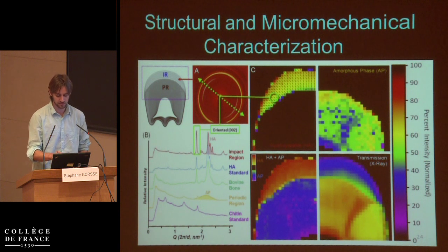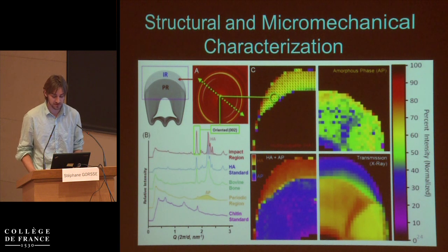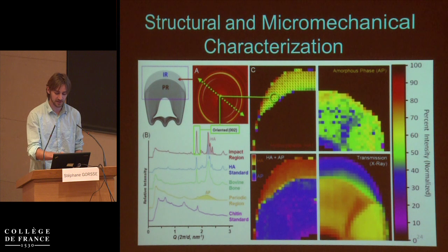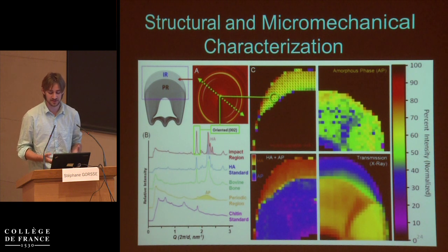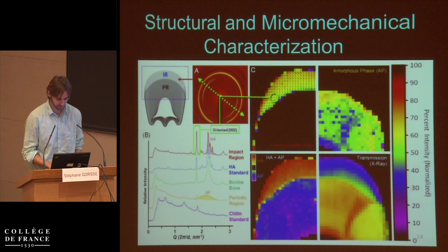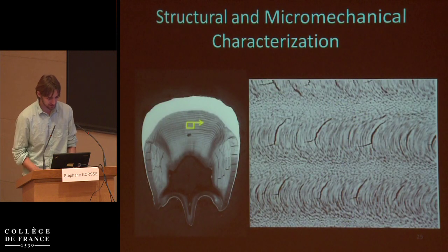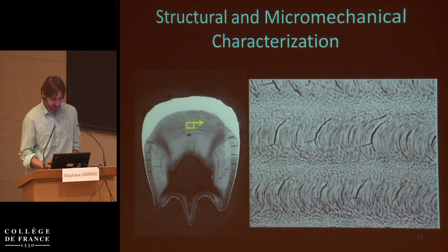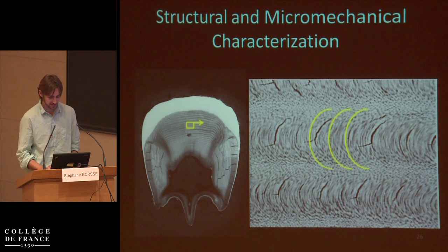And so the hypothesis proposed as to why you'd want a crystalline exterior is because crystals are hard. But an amorphous phase is actually easier to redirect and control a fracture because you're not limited to cleavage planes. And why that's important will become hopefully more obvious. So if we look into this interior, a polished cross-section, we see this characteristic C pattern. There's clearly chirality here.